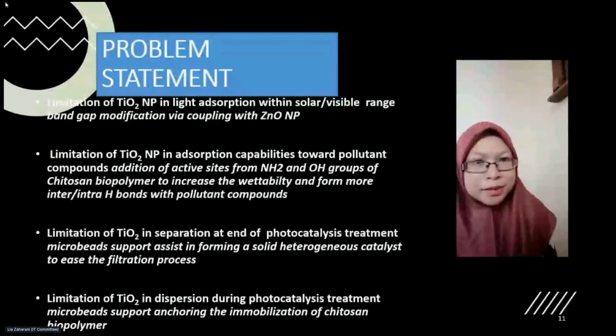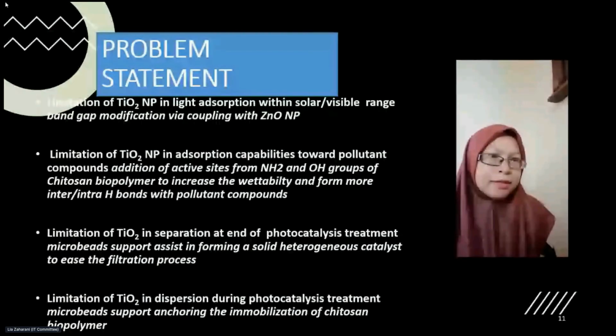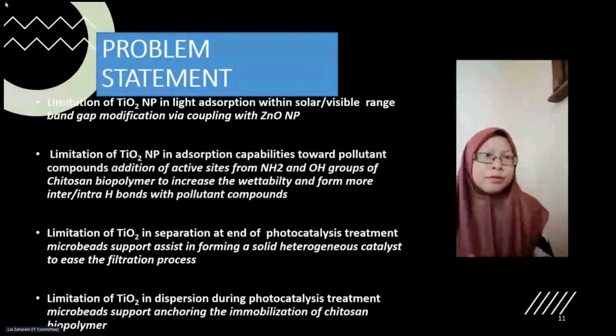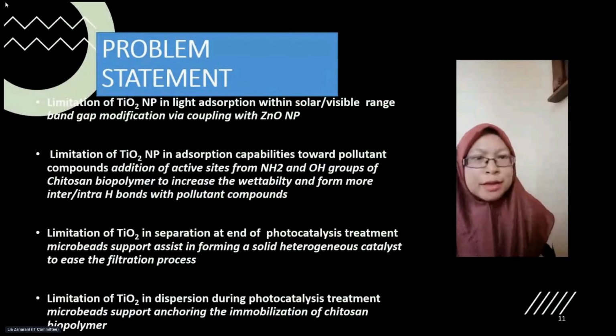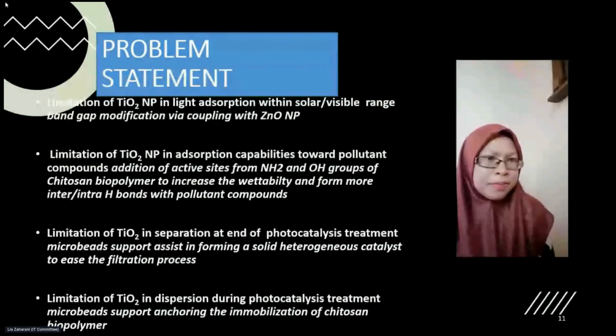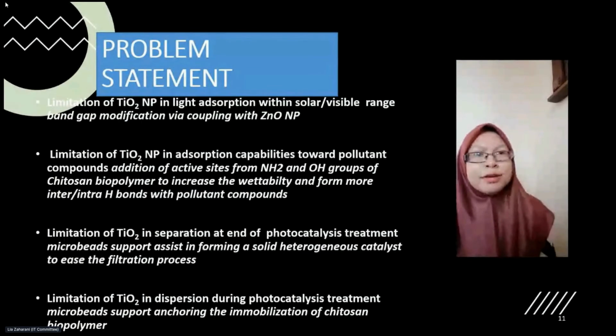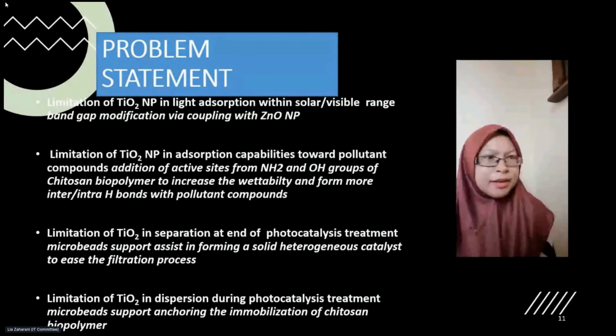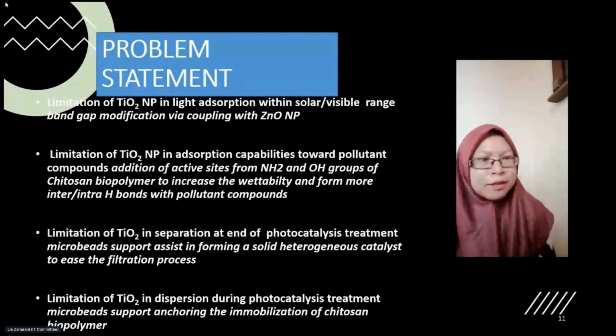It has also been reported that heterogeneous photocatalytic reactions are performed at the surface rather than in the bulk solution, and the surface properties of the titanium oxide are critical for the efficiency. Pre-adsorption on the surface of the titanium oxide particle is required for the efficient photocatalytic degradation of the dye, and more significant adsorption enhances the rates. This approach targets the use of supporting materials, such as microporous zeolite, mordenite, activated carbon, alumina, silica, and microporous silica on the surface. Hence, most of the photocatalytic activities were enhanced in these contexts.